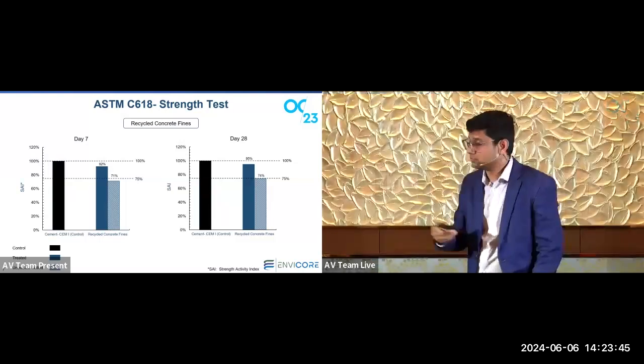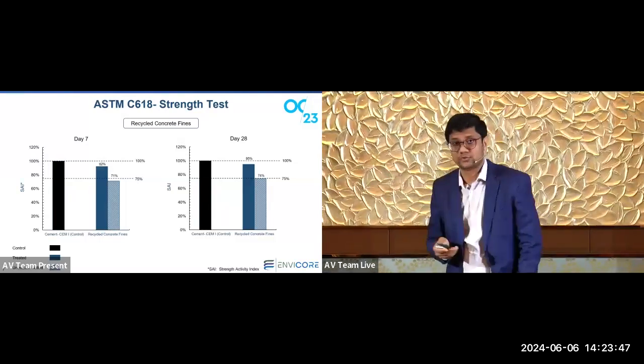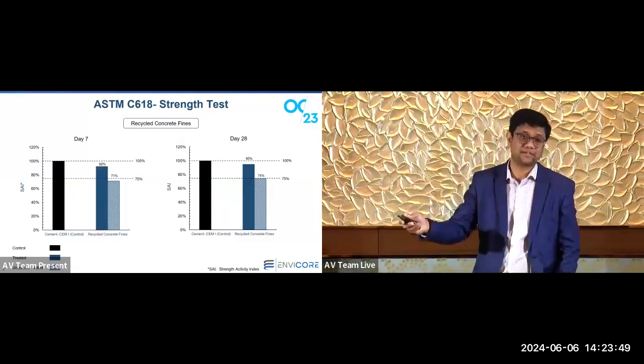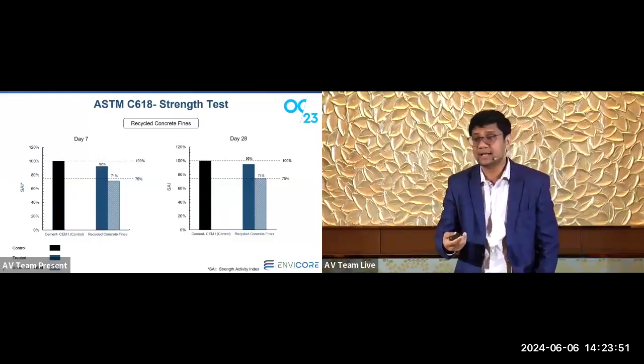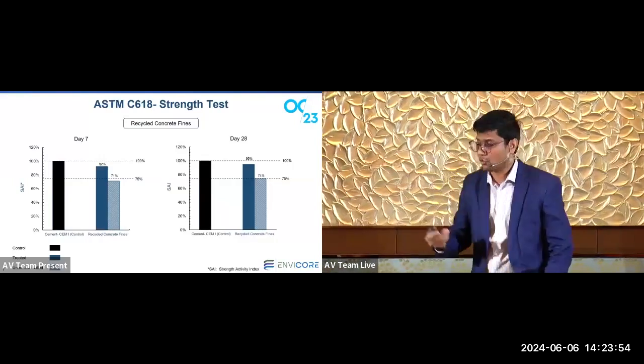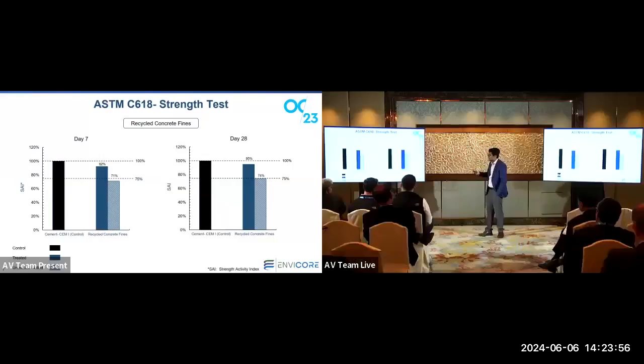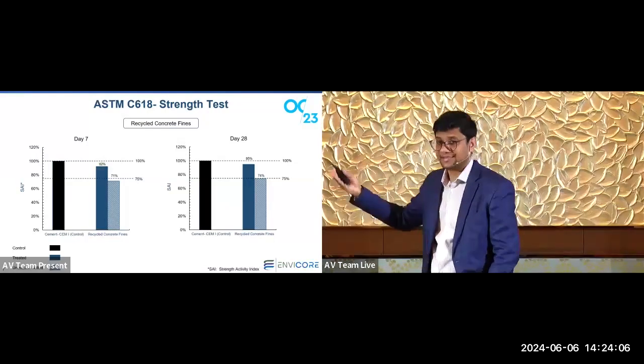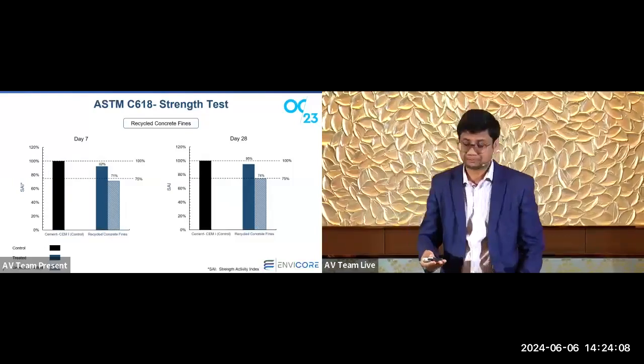The solid blue bar shows the processed material, and the checkered one shows the as-is material, but milled to the same extent, because milling does impart amorphization in the material. It's been reported many times in the literature. But in this case, we have shown that it went from 92% SAI at day 7, relative to control cement, to 95%, showcasing that it's considerably better than the as-is material, even after milling.